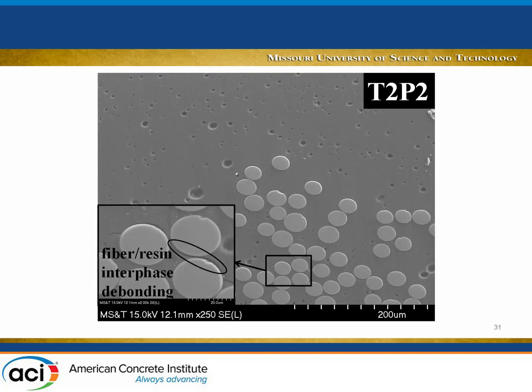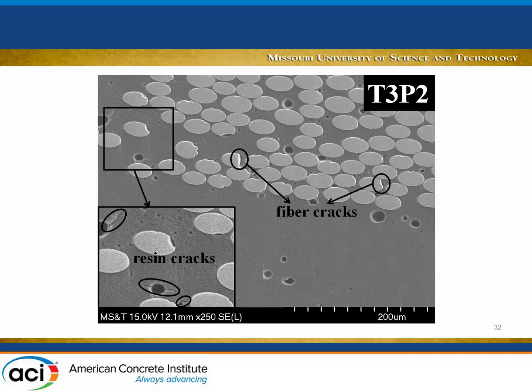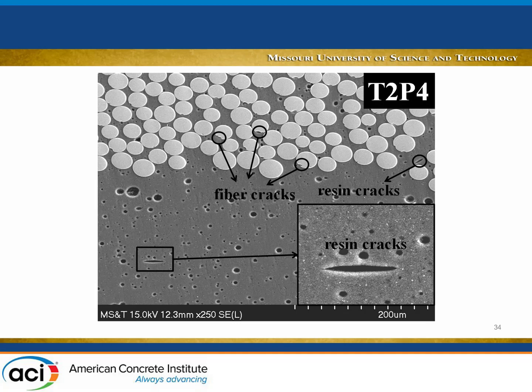As the temperature goes up and the duration gets longer, you start to see more damage. So let me show one of the worrying things here. For example, you start to see some resin cracks. This is tank 2, at a little bit higher temperature for a year of exposure. So you start to see some resin cracks.